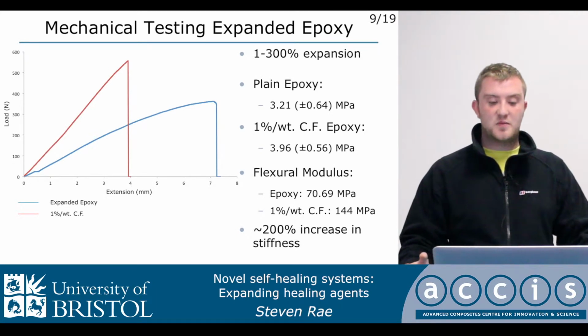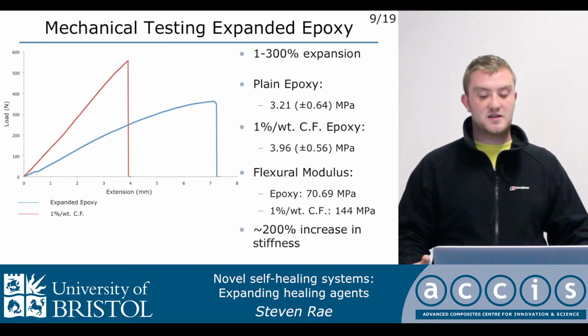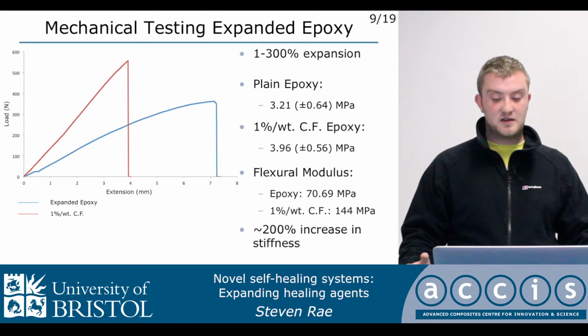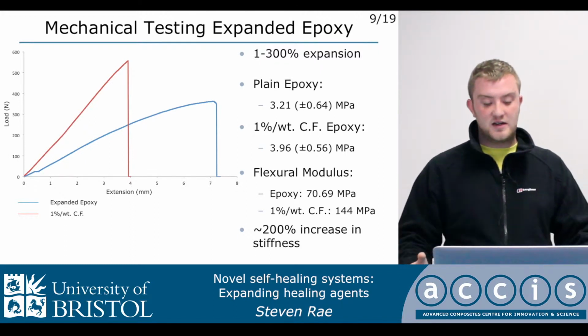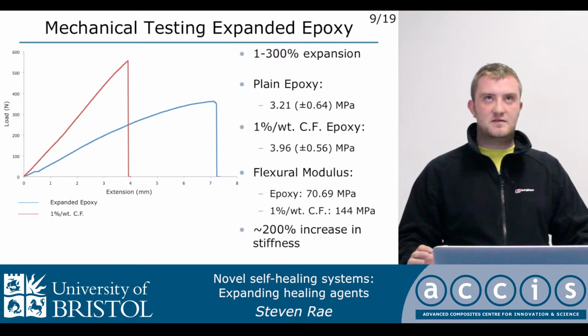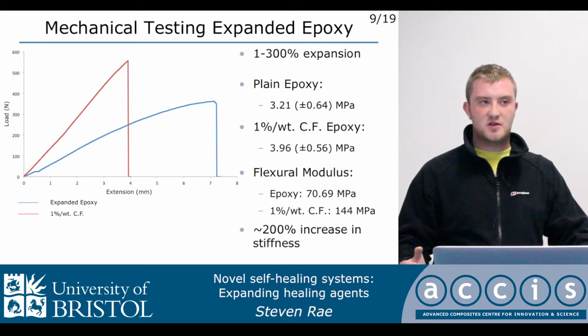So to test the mechanical properties of each of these epoxy-based systems, we performed flexural testing, and we got the strength and the flexural modulus of these systems as shown here. In expanding a healing agent, we were concerned that in expanding the volume, we would lower the properties. So we thought, how can we mitigate against that? And one of the ideas was to incorporate chopped carbon fibre into the system to try and mitigate against this drop in performance.